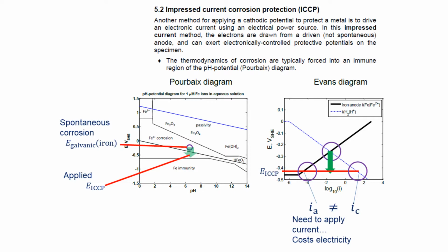In fact, it would even be potentially worse, because if we have a larger amount of hydrogen being evolved, we have a greater risk of hydrogen embrittlement taking place. And that's something which we can easily cause to happen by accident with an impressed current cathodic protection system.